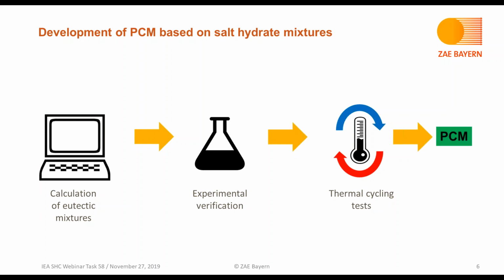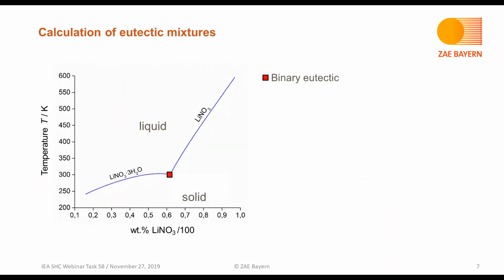the predicted eutectic composition needs to be experimentally verified. If this verification is successful, we are performing thermal cycling tests to test the material under application conditions. And if these tests are also successful, then we have successfully developed a new PCM. So for the first step, the calculation of eutectic mixtures: why are we doing this?